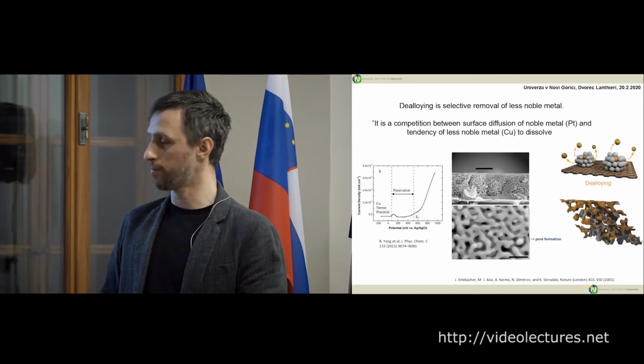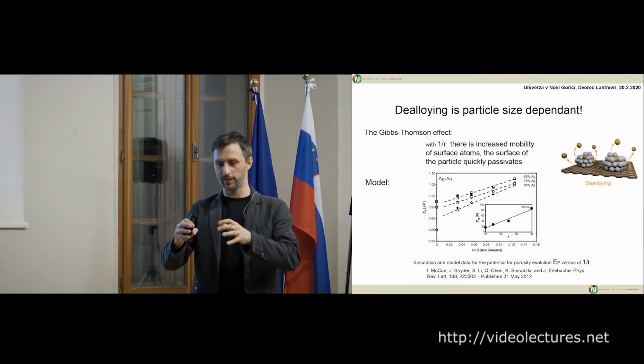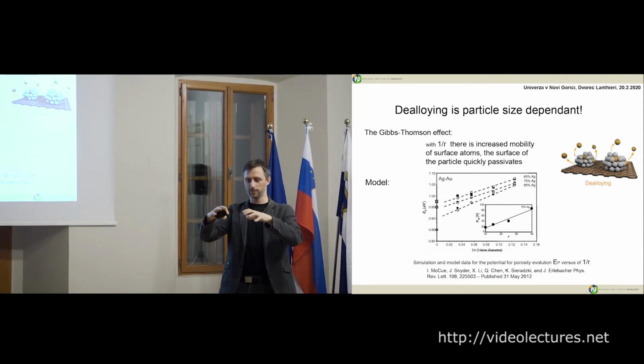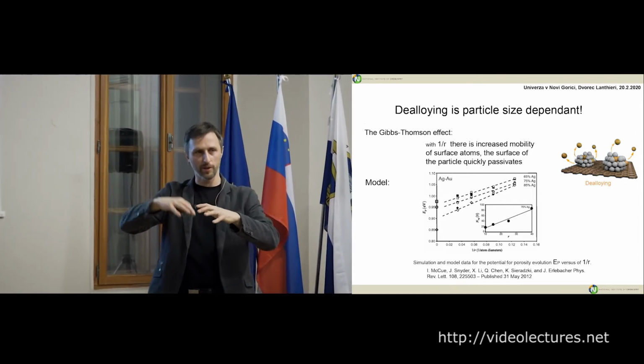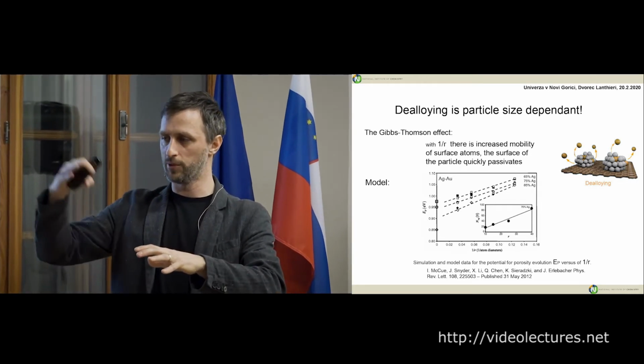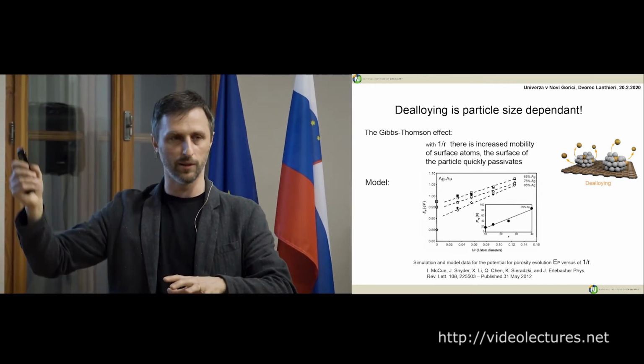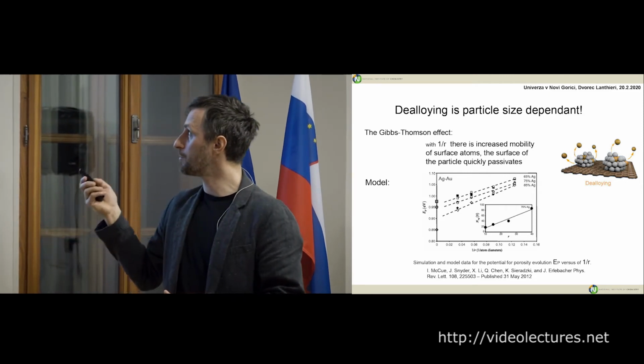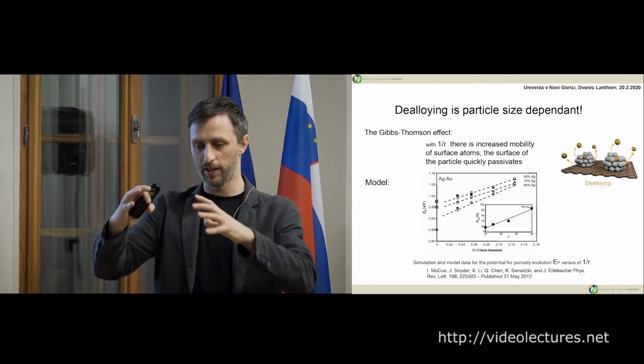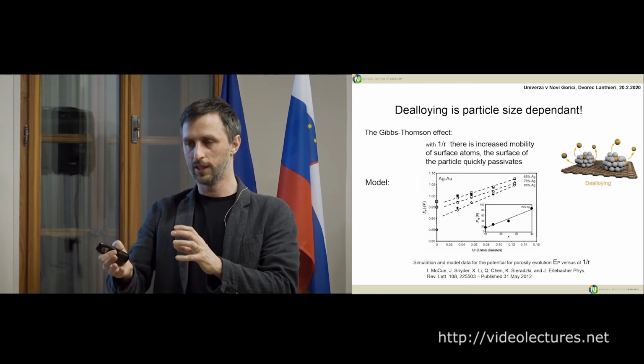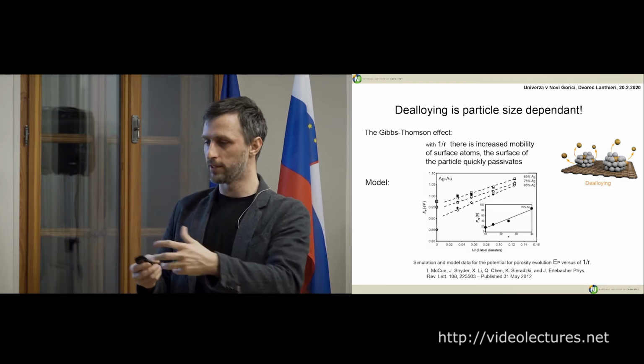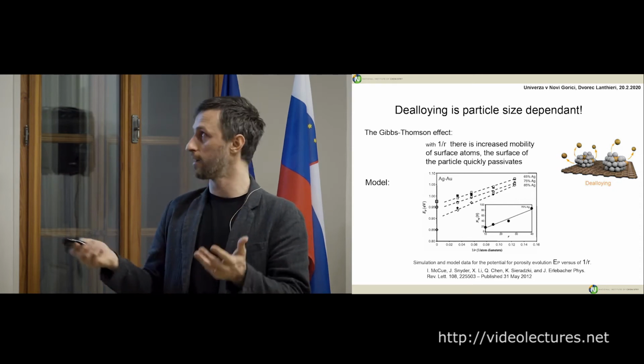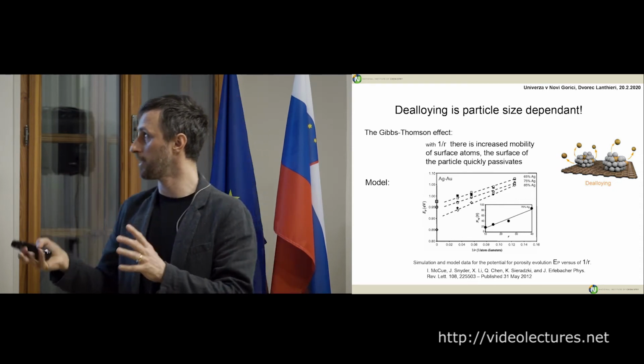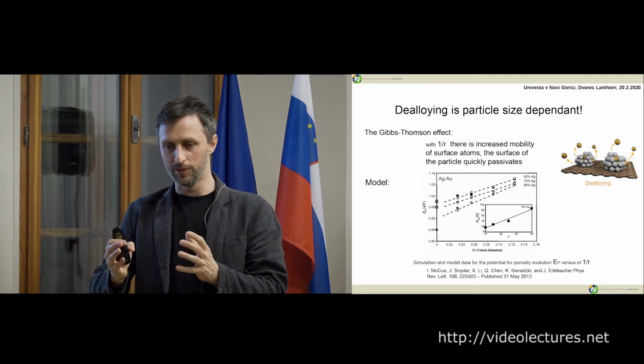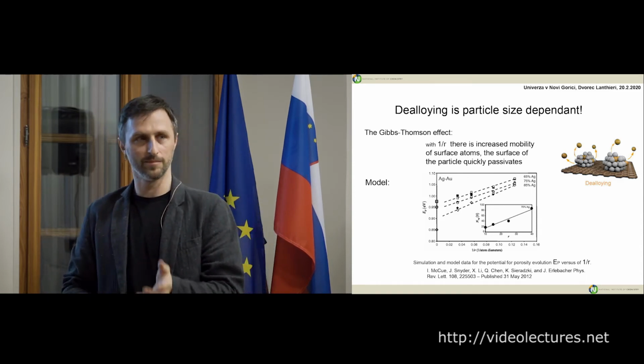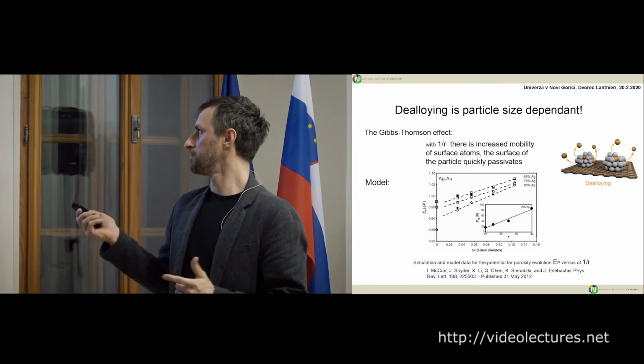What's also interesting here is that this mechanism works because you have surface diffusion of platinum, which is protecting copper inside, and then at a certain point when you raise the potential enough, the copper is forced to go out. And I'm telling you this here because if you have nanoparticles and go to smaller dimensions, it seems that the movement of the surface atoms is higher. So this is kind of Gibbs-Thomson effect. It means if the particles are smaller, diffusion will be higher. This will come later.